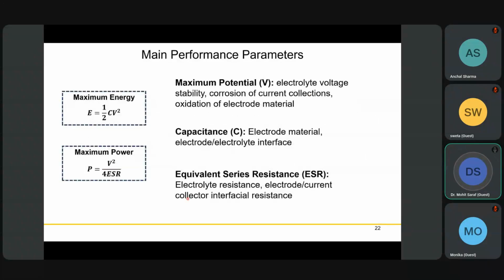There are some parameters to check in supercapacitor testing: energy, power, the maximum potential window you can get, and capacitance. Then there's equivalent series resistance, which governs the electrolyte resistance, any interfacial resistance, or resistance between internal components of your cell, like current collectors. There are also other kinds of resistance, for example solution resistance and charge transfer resistance, which we usually study by electrochemical impedance spectroscopy.